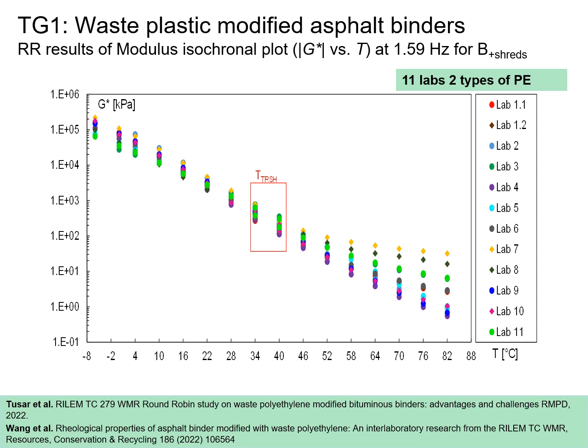And here, this example shows you the round robin results showing modulus compared to the temperature. And you see that when we look at lower temperatures, up to about 40 degrees, the results of the different labs coincide. However, once we go above 40 degrees, the results seem to diverge. Although we have used the same grade of binder and the same type of PE, here we're talking about a waste material that is inherently not homogeneous. Once we are at colder temperatures, the whole blend behaves elastically. But once we go above 40 degrees, we have an elastic material, the PE, in a viscoelastic material. So our binder starts to become softer, whereas the polyethylene remains elastic. And so the difference shows up a lot more.